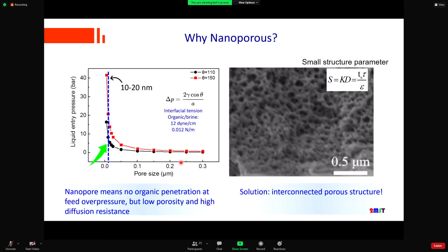Why nanoporous? This is the Young-Laplace equation giving us a liquid entry pressure for the organic to enter the hydrophilic membrane. So we need a very small pore to block the entrance of the organic extractant into the hydrophilic polymeric membrane. But because we have a nanoporous membrane, the resistance of the lithium ion diffusing will be high.